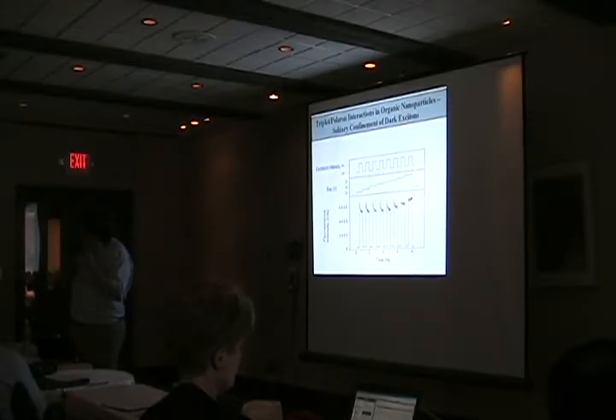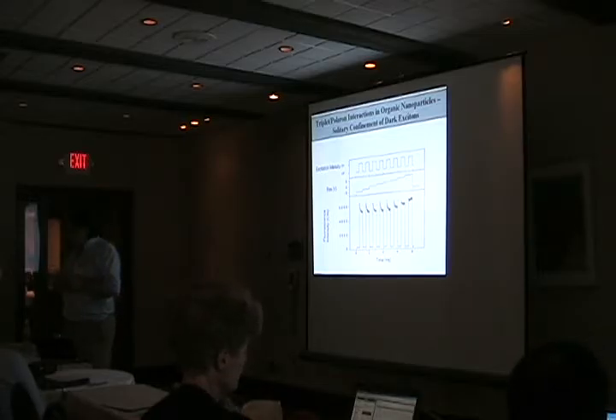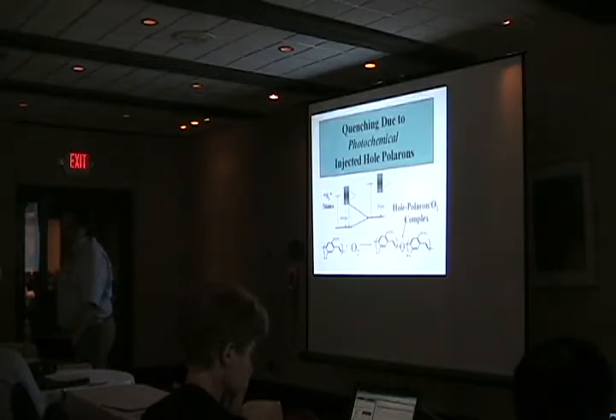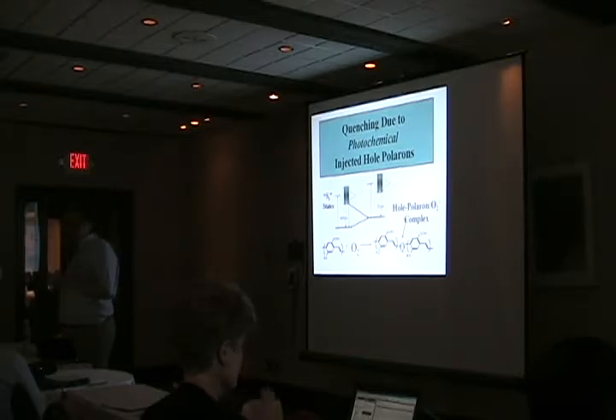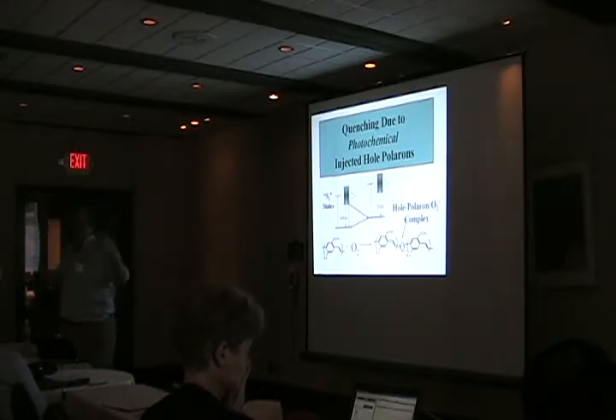bias on the electrode. And by doing that, sorting out the quenching of the triplets and the singlets. In other words, the dark excitons and the light excitons. And that's an interesting story for the chemists. Triplets are quenched with tremendously higher efficiency than singlets. But that's because triplets live a long time. The actual rate constant is higher for singlets than triplets. But triplets live so much longer that the efficiency of quenching by charges is almost 100%.